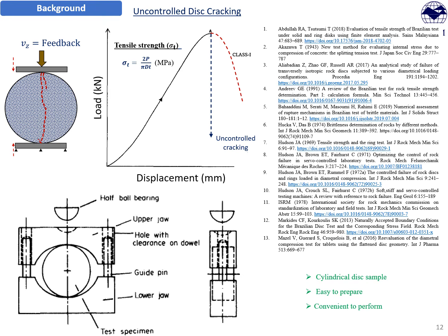However, in the literature we have seen, and in laboratory experiments also we have seen, that often the crack does not initiate at the center of the disc. Instead it initiates at the loading ends because of high localized compression. Now, in those scenarios where the crack is not initiating at the center of the disc specimen, the reliability of tensile strength estimation can be debated. The second aspect is its uncontrolled dynamics.